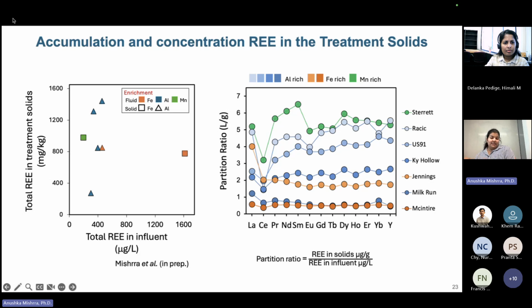Versus for the irons, we see consistently low partition ratio. So if we were to design an extraction process using an iron enriched AMD fluid, the amount of REs we can extract may just be lower based on these estimations. The aluminum seems to be at a broader range where we can see high partitioning happening for active treatment systems, whereas low partitioning happening for maybe some passive treatment systems. So this is for individual REs and yttrium, but yeah, we can start seeing some trends develop for different types of rare earth elements present in the system.